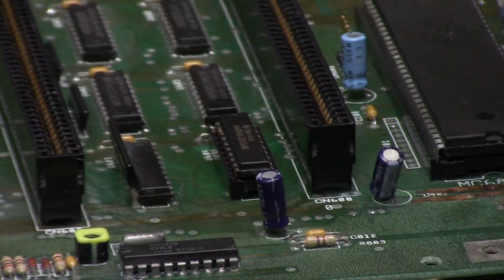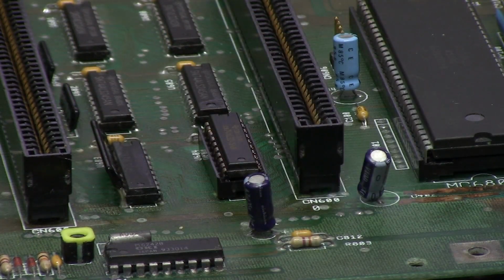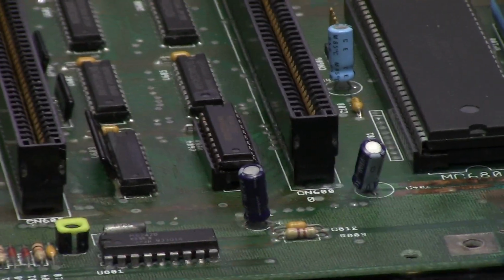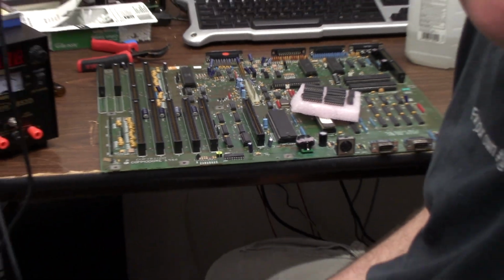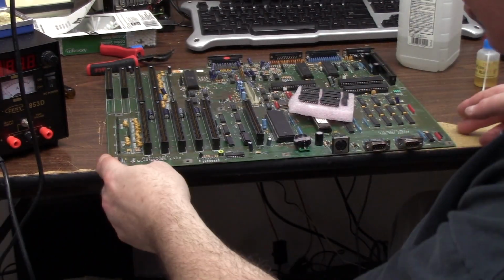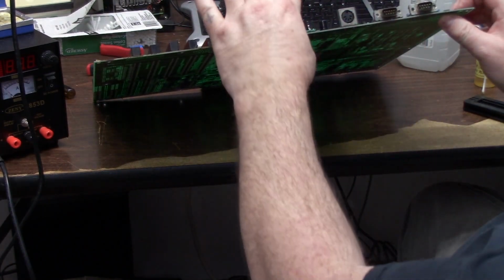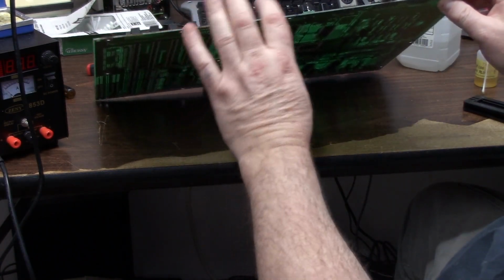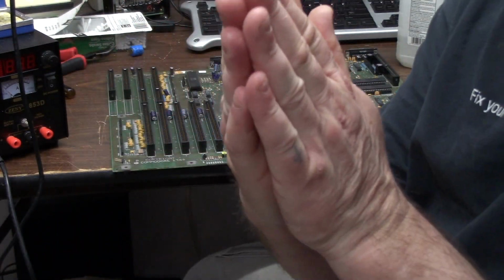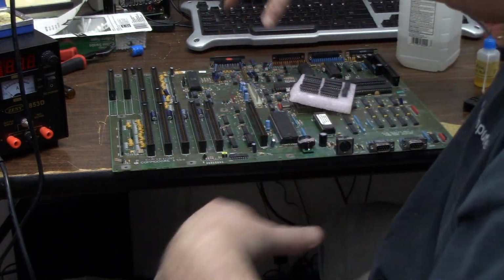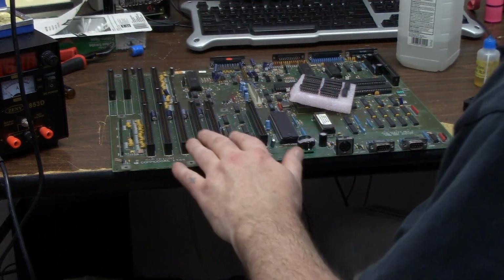A nice socketed, but I would not recommend using heat on a 30-year-old board due to risk of delamination. I don't know if I can even show this, but this is a piece of fiberglass. Basically, there's a layer on the top, there's a layer on the bottom, the circuits run through it. Bob's your uncle. If you heat that up, it can go like this, and the heat will spread, and you can have a runaway and lift more traces than you can imagine. That's why I don't use heat.